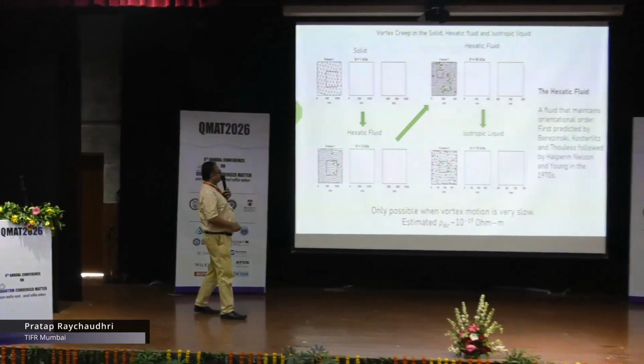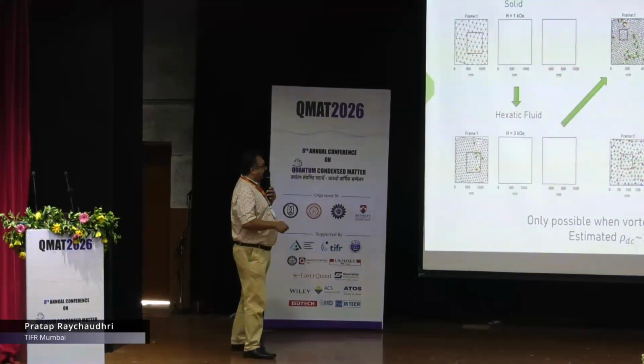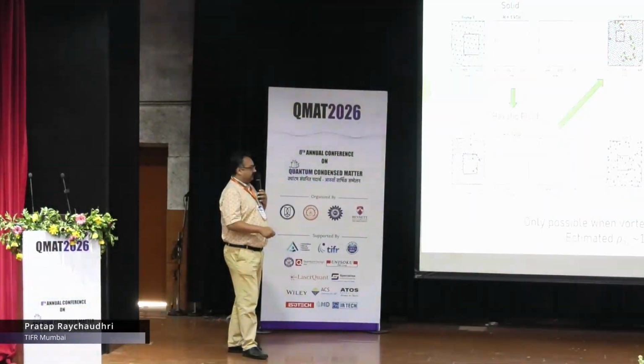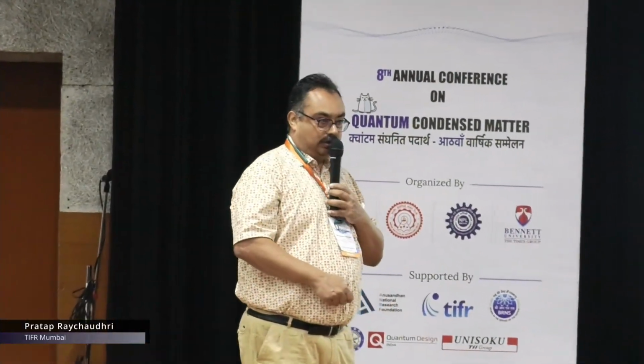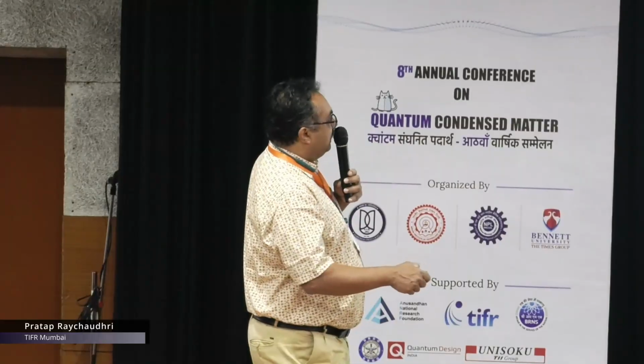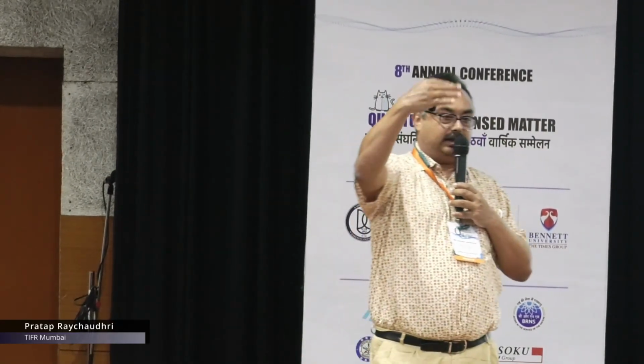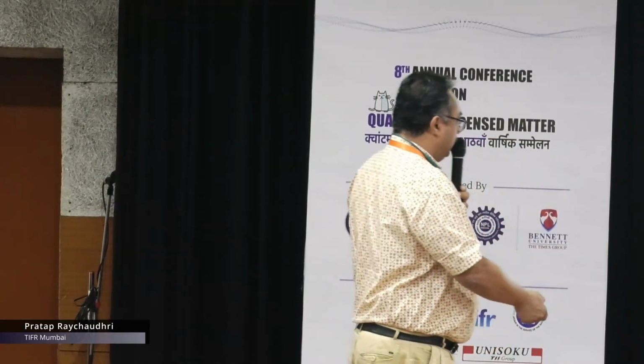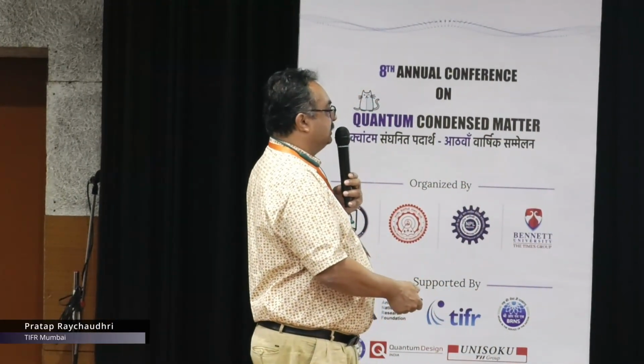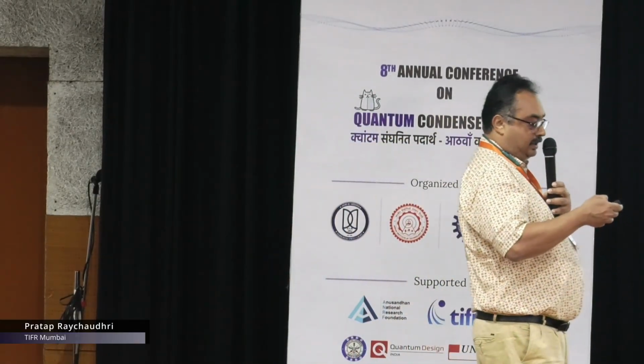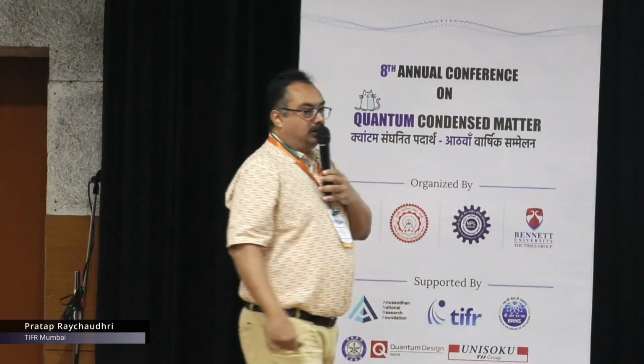Now, however, you can see that I can do this kind of imaging and track the motion of vortices only when the motion is very slow. And that means that if I now pass a current, the vortices will start moving and I will have dissipation, but the dissipation will be enormously small, and the estimated DC resistance will be of the order of 10 to the power minus 19 ohm meter. This would mean that there is not much implication for transport.